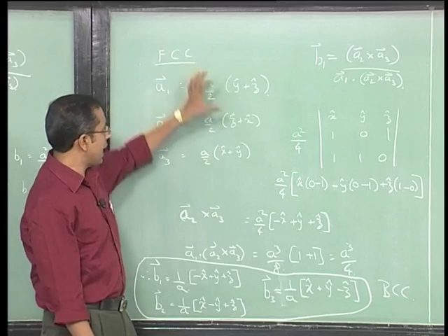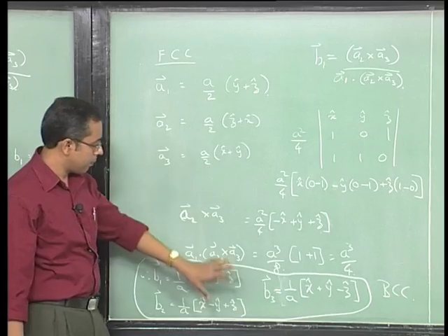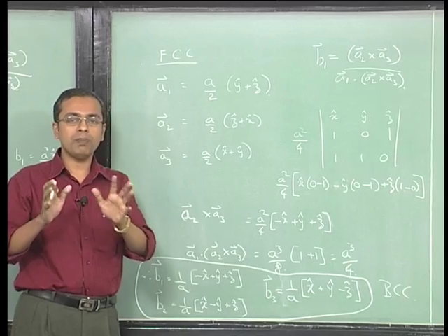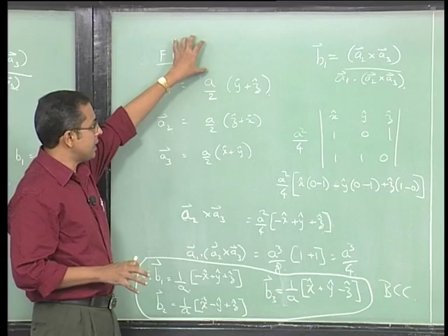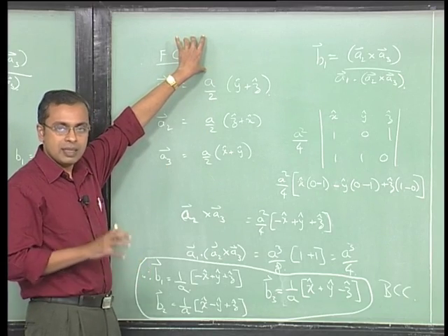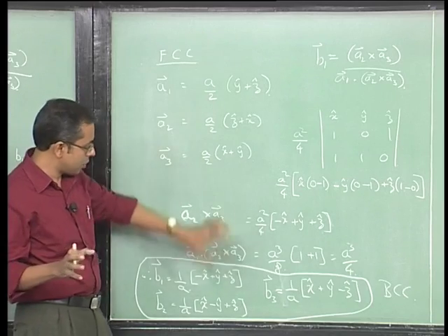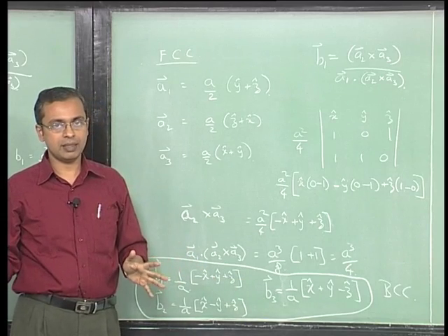So if you have a sample that is face centered cubic, you will have to plot the points in reciprocal space the manner you would do for a body centered cubic material. We are only talking of geometry. Geometry in real space is face centered cubic. This same material when represented in reciprocal space will have a geometry similar to that of a body centered cubic material.